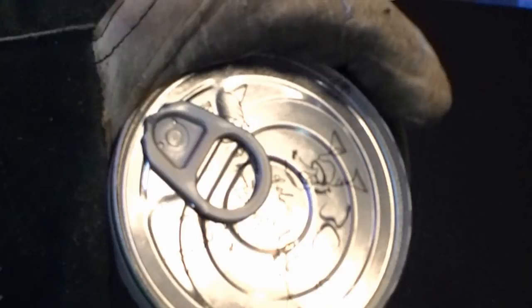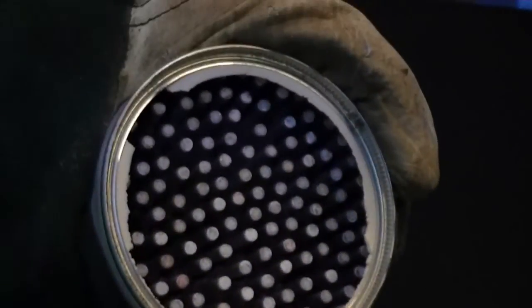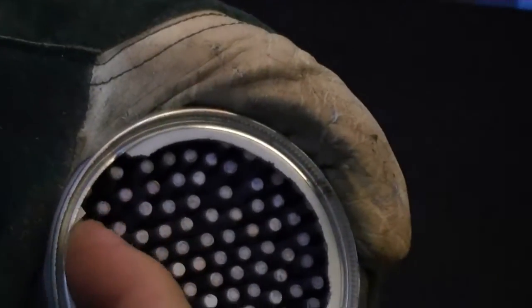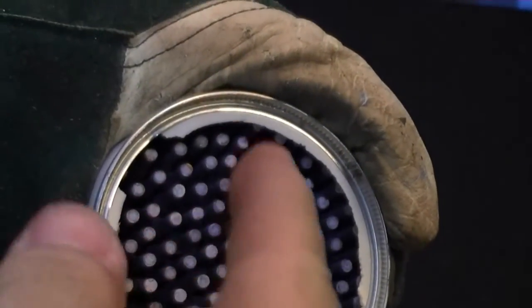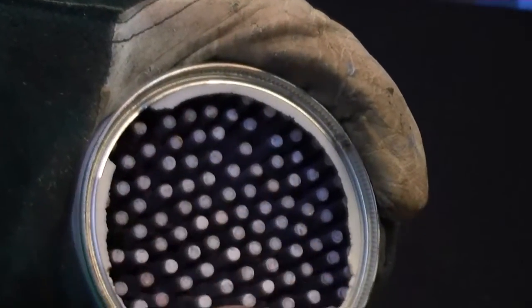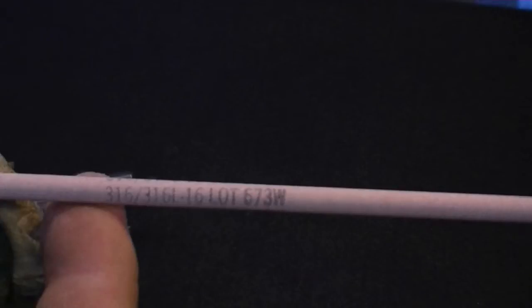Stainless steel electrodes are similar to low hydrogen steel electrodes and should be kept in a rod oven or used fresh from a sealed container like this one. We will be using a 1/8 inch diameter electrode for the demonstration.